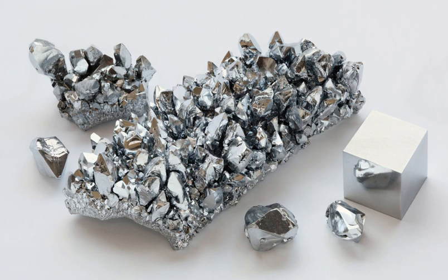Chromium has an unusually high specular reflection in comparison to that of other transition metals. At 425 nanometers, chromium was found to have a relative maximum reflection of about 72% reflectance, before entering a depression in reflectivity, reaching a minimum of 62% reflectance at 750 nanometers before rising again to reflecting roughly 90% of 4,000 nanometers of infrared waves.